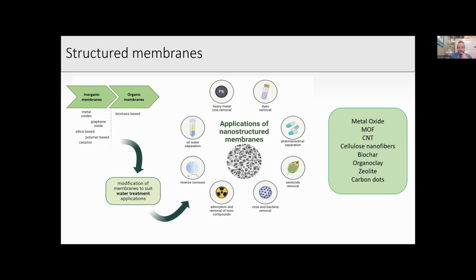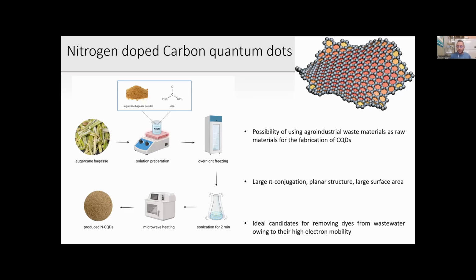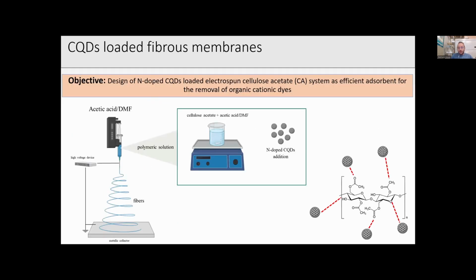But in the last decades, carbon quantum dots appear to be an interesting class of material, since they can confer specific adsorption sites for the removal of a wide class of contaminants. In this case, we use nitrogen-doped carbon quantum dots produced by using an agro-waste resource such as sugarcane bagasse. This is a work in collaboration with the National Research Center of Giza in Egypt. And in this case, a novel and sustainable approach was used to fabricate and to dope the carbon quantum dots, which were used as filler inside the cellulose acetate electrospun membrane to design a novel class of membrane as a barrier for the removal of a specific contaminant from wastewater.